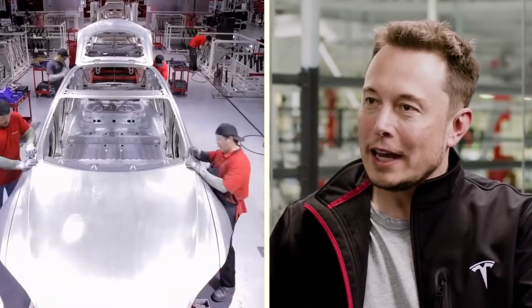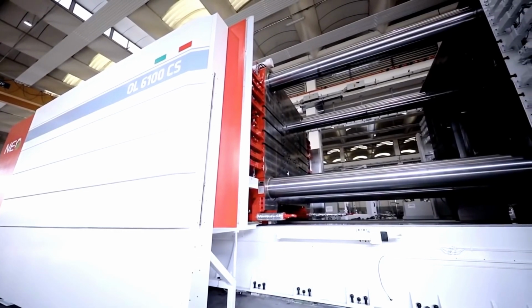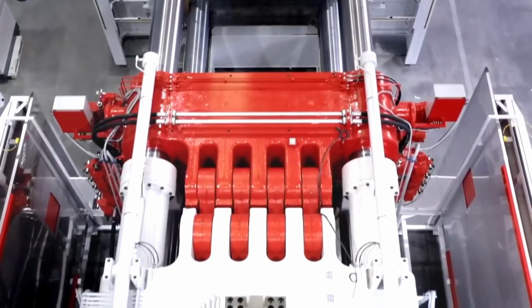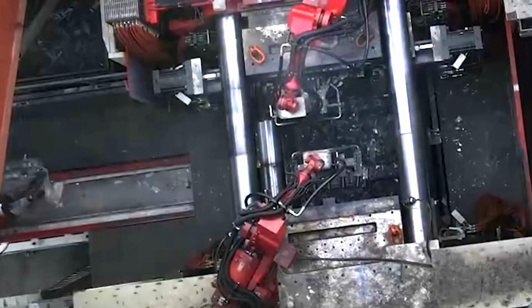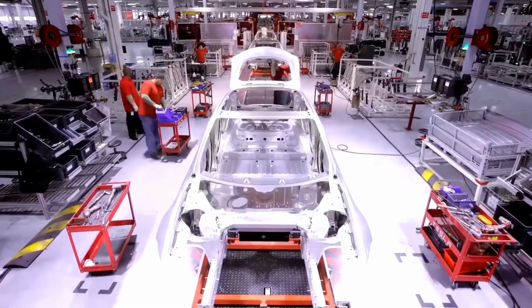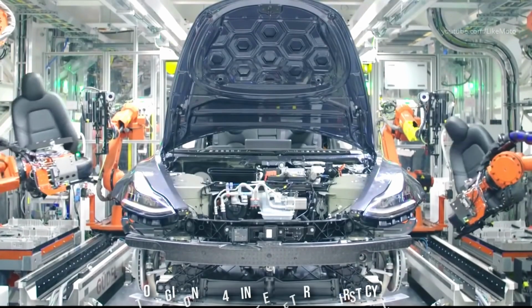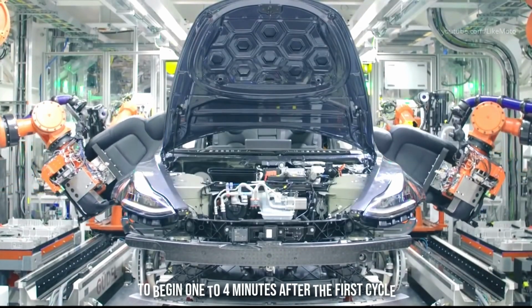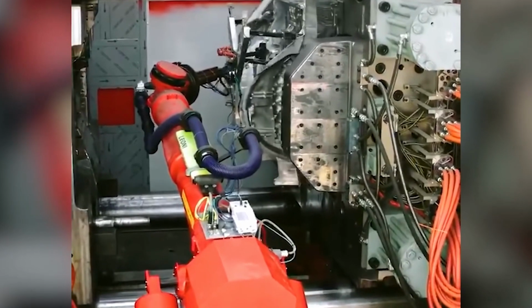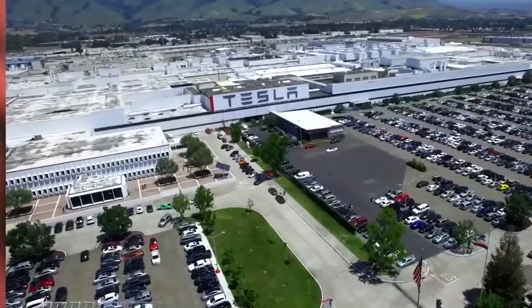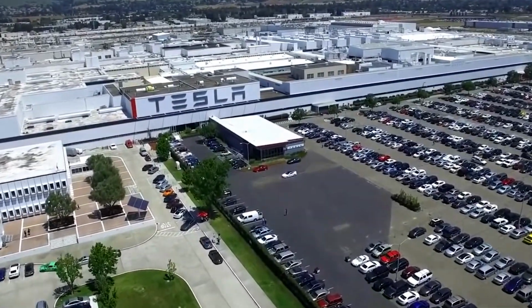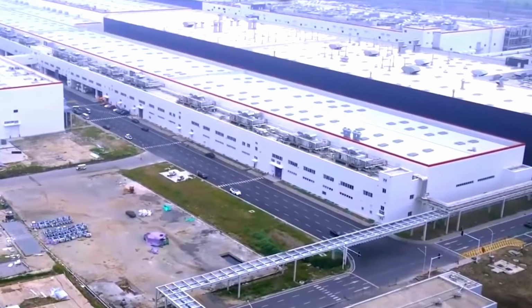How does die casting work? Well, it works by forcing molten metal alloy inside a reusable mold and then opening the mold to remove the finished piece after it has solidified. The open mold is cooled to 185 degrees Celsius and cleaned by robots, and fresh molten aluminum is prepared for the next cycle to begin 1 to 4 minutes after the first cycle. Each fresh casting is trimmed to approximate size, measured, checked for imperfections, and sent for machining to be fully polished and finished by another machine.